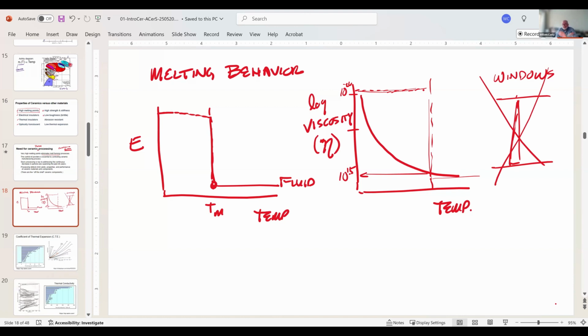So there are a number of points in viscosity. If you go to the glossary, which I mentioned at the beginning, in the back of the glossary is a list of defined viscosity values for glass. But this is our glass here, and we have this continuous curve of viscosity. That allows us to do melt forming.